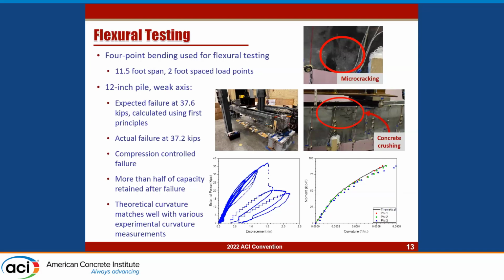We instrumented the pile with a lot of different types of instrumentation. We used those previously mentioned strain gauges. We also applied some external strain gauges, string potentiometers, LVDTs, as well as an LED system that is non-contact and will measure the displacement while we test. And we took all of those instruments and all the data that we got from that, and we plotted the moment curvature 3 different ways and compared it to our theoretical moment curvature. That's this graph on the right over here. And you can see that they all agree pretty well.